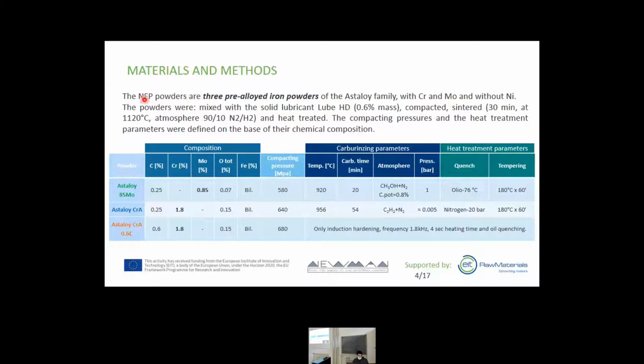The tested powders are three pre-alloyed iron powders of the Astalloy family. The first one, the 85MO, is alloyed with molybdenum and 0.25% of carbon. And the other two powders are CRA powders alloyed with chromium. The first one has 0.25% of carbon, while the last one has 0.6% of carbon. All the powders were mixed with the solid lubricant, and then they were compacted and sintered. The first two powders were carburized and heat treated, while the last one was just induction hardened.